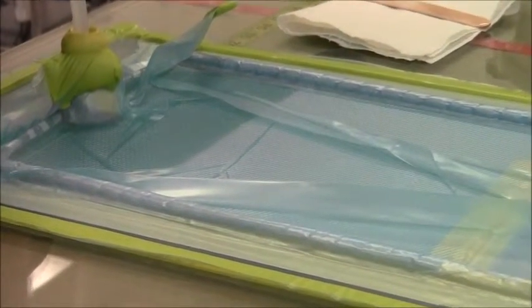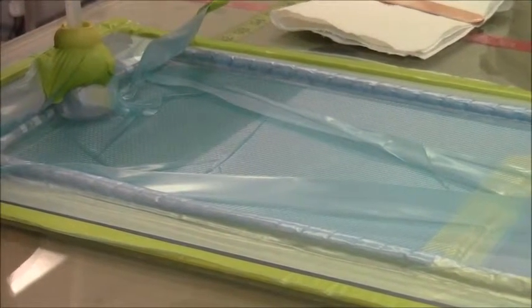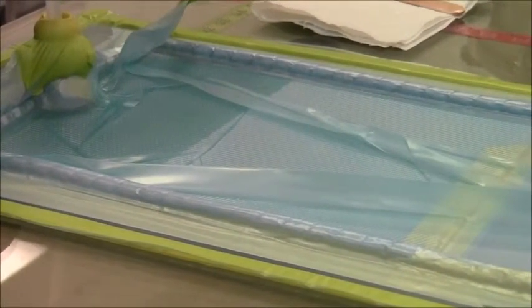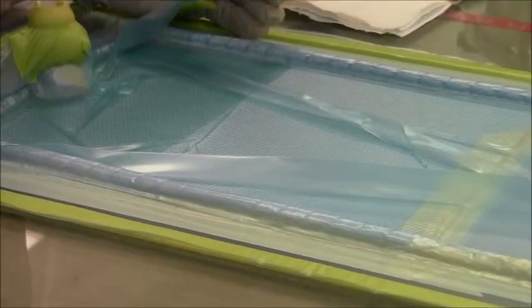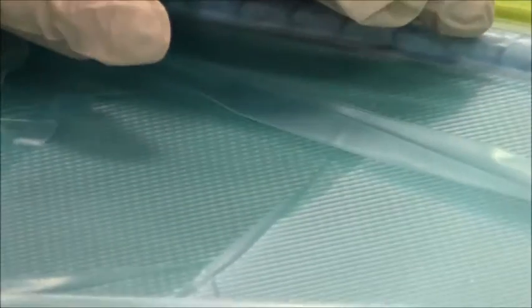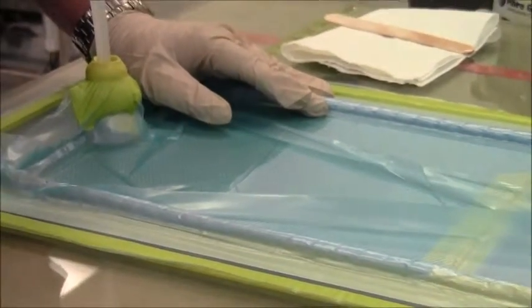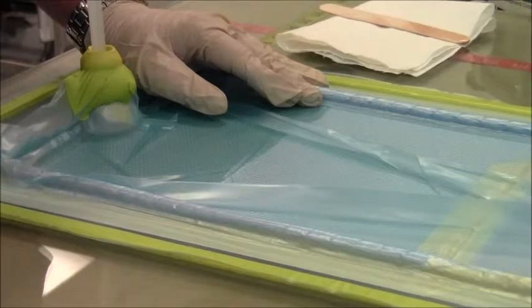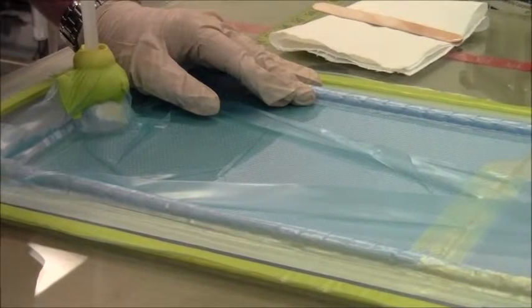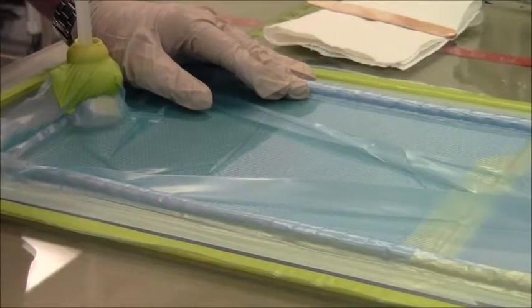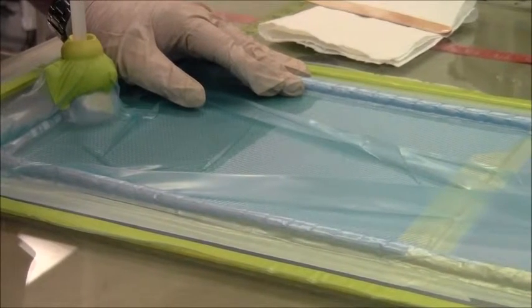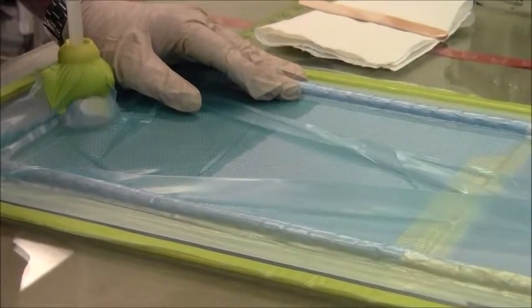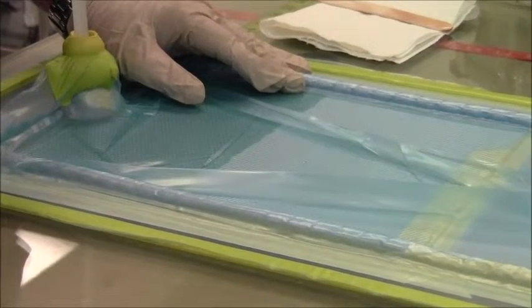The further in you go with the infusion, the need for a quick bump, and then allow that to go ahead and flow out. A very close look, you can see that there's absolutely no air or gas migration whatsoever within this infusion. This is telling me that even though we haven't used a veil on this particular part, which most of the times we do advocate, because we're using a glass surface where we have a very, very nice surface tension, we can get a very good finish on a 100% Innegra part against a premium surface.